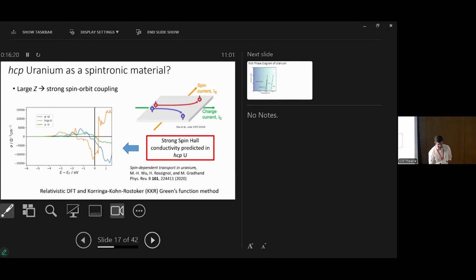So one of my colleagues, Martin Gradhand in Bristol, predicted that it should have a very large spin Hall conductivity. So for things like the spin Hall effect, it should have a very large spin Hall conductivity. Again, because it's a large element, strong spin orbit, as we heard in the last talk. Actually, Martin did this for 3 different crystal structures: the alpha orthorhombic phase, the hexagonal close pack phase, and the gamma, which is the BCC uranium phase. And actually the HCP phase, this orange curve here at the Fermi energy, showed the largest predicted spin Hall conductivity. So that was a theoretical prediction.